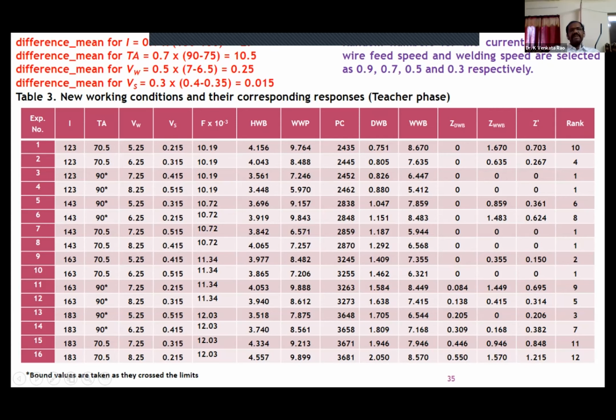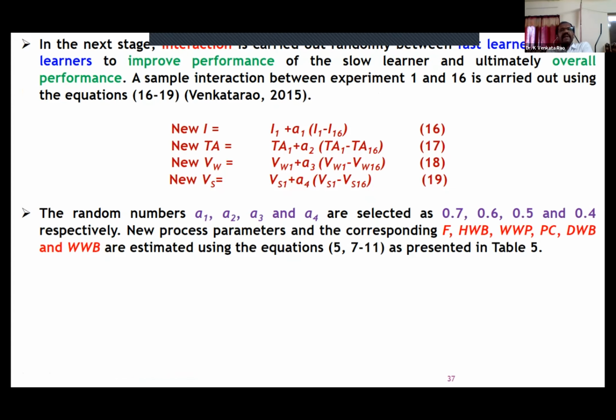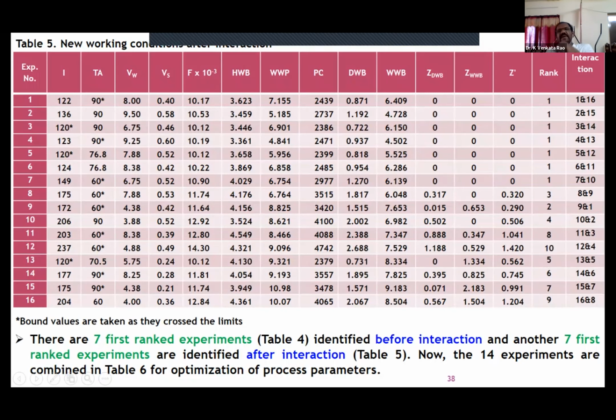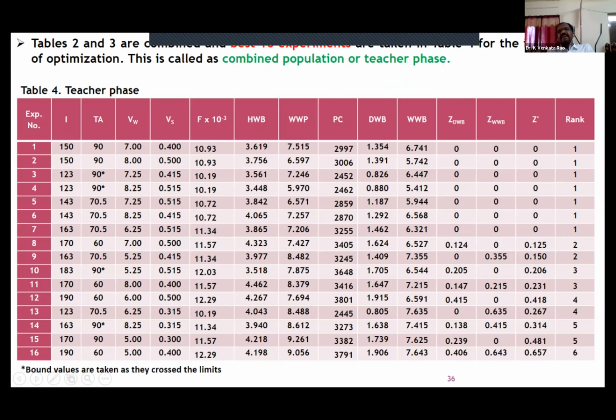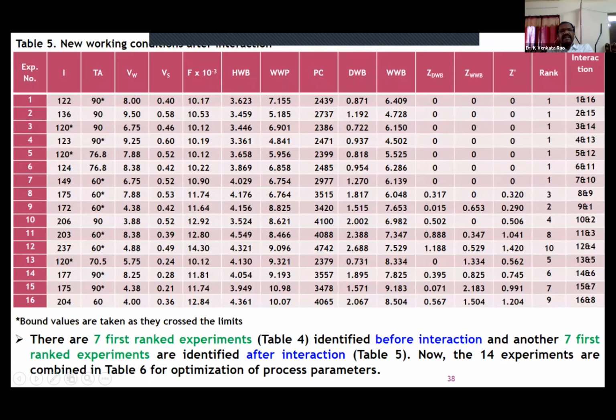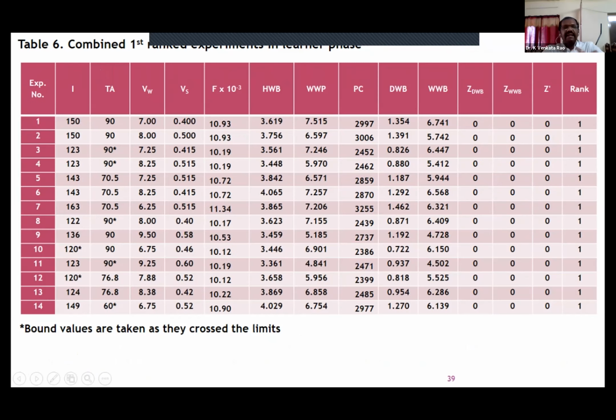So here we got the new process parameters using the equations that I already told you; again new responses were found, again ranks were assigned. So this one is the teacher phase, and this one is the interaction phase. New process parameters were found using that equation, responses were found, these constraints were also found, and here we got the 7 best ranked students in the interaction phase. Before this, in table 4 you have the 7 best ranks, and after interaction also you have 7 best ranks. These 7 plus 7, 14 best solutions we got. So based on the ranks, we found 14 best solutions here.